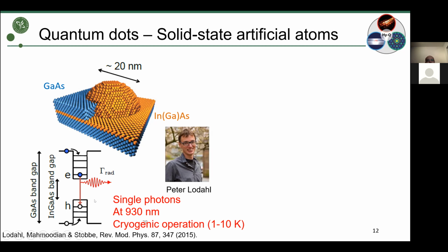And the typical emission wavelength here is about 930 nanometers, so red, near infrared. And it typically operates at cryogenic temperature. Here, I would like to stress this fact a little bit, because many people ask, can I make an emitter that works at room temperature? It's actually very hard, because at room temperature, you have a lot of mechanical motion, you have thermal excitation. And so all these levels are actually blurred, because this quantum well is shaking continuously, right? So you cannot really get indistinguishable photons from an emitter at room temperature.